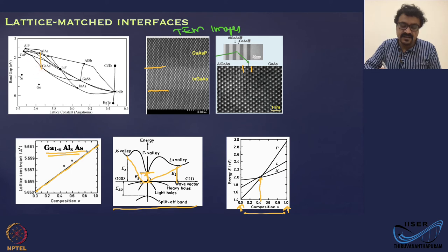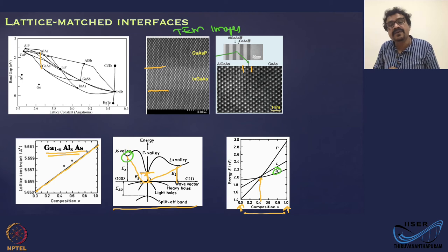Gallium arsenide is here, aluminum gallium arsenide here. You need to go from here to here when you vary x from 0 to 1. What that means is your band gap is actually increasing. At some point, around 0.4, the band gap is actually above the X point, but X is an indirect band gap. That's the X value here. That's the indirect band gap. So what that means is the material is actually changing from direct band gap to indirect band gap.